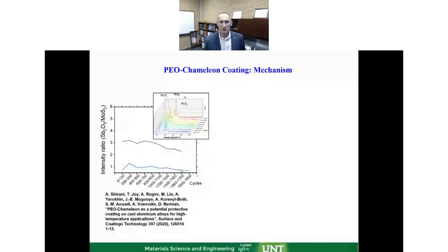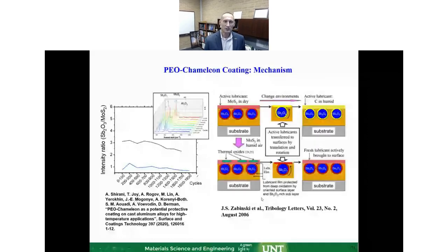Well, to answer that question, all we need to do is go back to the literature 14 years ago. Jeff Zabinski was looking at these chameleon coating compositions, working with this composition using transmission electron microscopy, doing post-mortem analysis, not in situ. They formulated this mechanism: antimony trioxide rotates and dislodges during the friction and moves downward, leaving the surface richer in molybdenum disulfide. So 14 years after that publication, we confirmed that mechanism shown here.